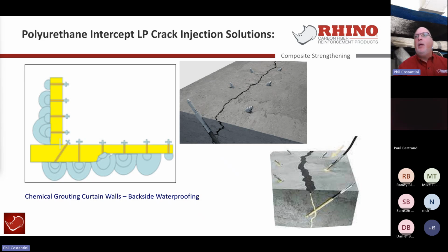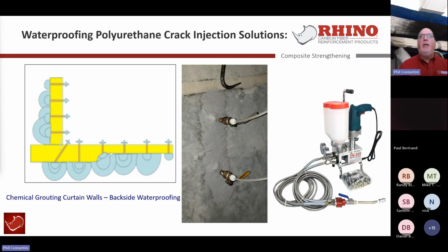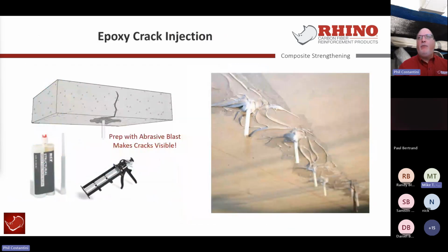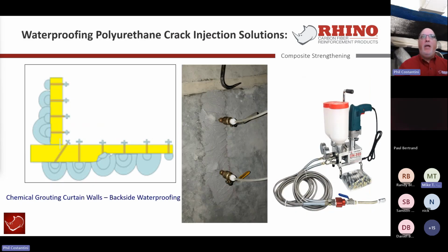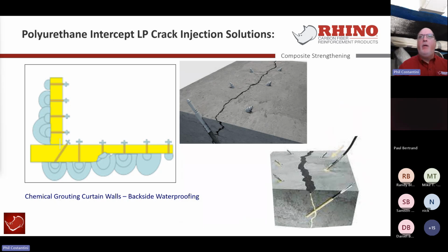penetration moving forward. The key element here is when you're done there, make sure you're utilizing a structural mortar or an epoxy grout to fill the surface of that crack back in long before you put any type of carbon fiber reinforcing on it. So epoxy to establish and reestablish the glue line in a regular reinforcing scenario, polyurethane hydrophilic hydrophobic foams to create backside waterproofing with either low pressure or high pressure grouting.